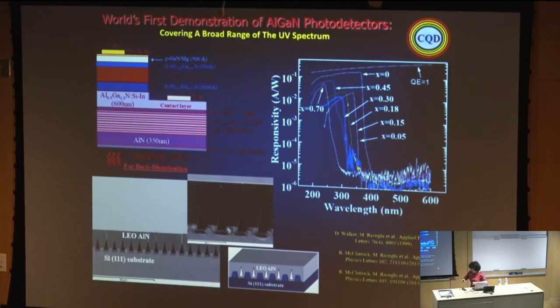Very similar structure. So here we have responsivity as a function of wavelength by changing the composition of aluminum in the aluminum gallium nitride PIN detector. As you can see, very nice detectors with different wavelengths from 200 nanometers up to gallium nitride at 400, with 4, 5, 6 orders of magnitude rejection ratio. But here is the theoretical limit of the quantum efficiency, that is 1 for the PIN, as you can see here.